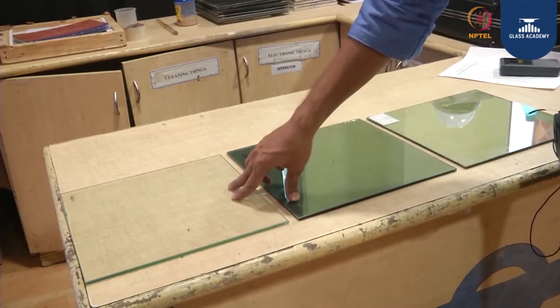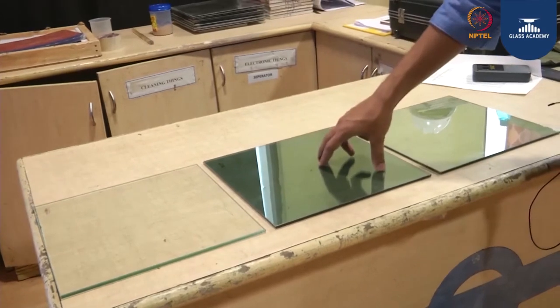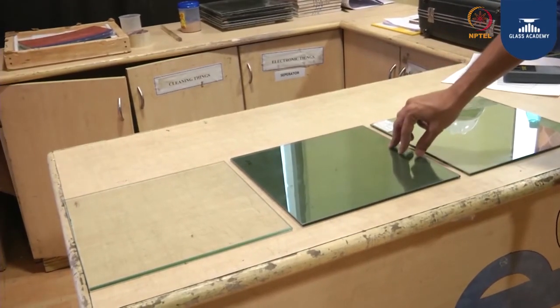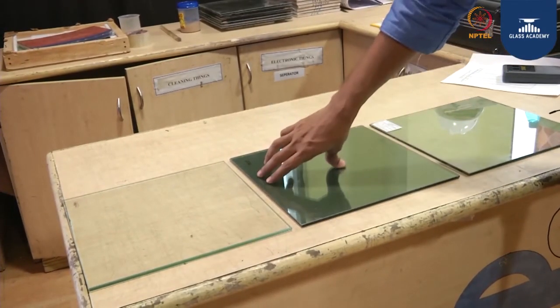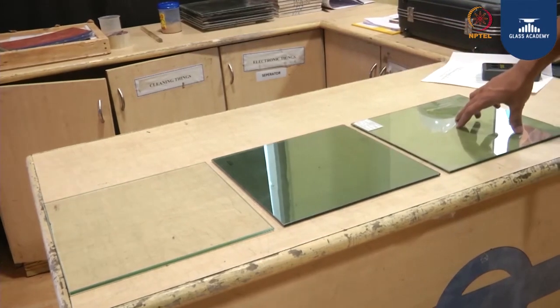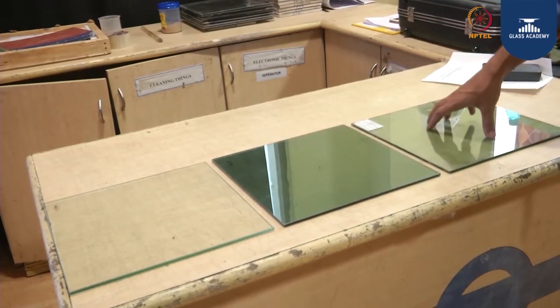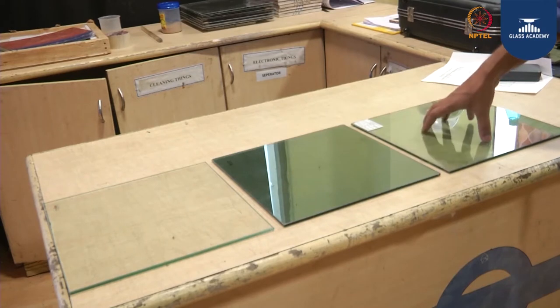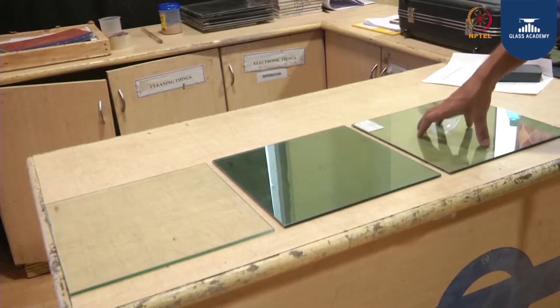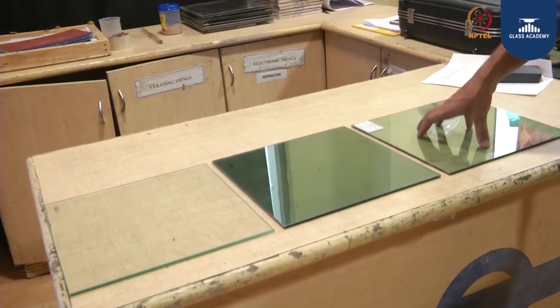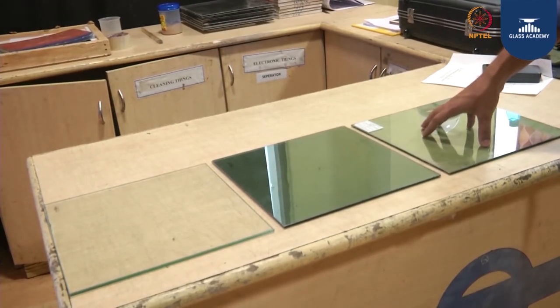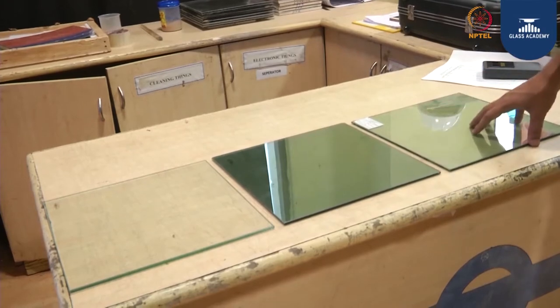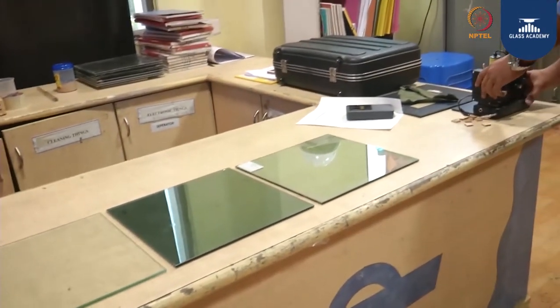When I break a toughened glass, it will break into small fragments. When I break a HS glass, from the impact point, the crack will end at the opposite edge. When I break an annealed glass, it has an irregular shape and the pattern can be anywhere. That is a destructive method of testing. If a glass breaks at the site level, we cannot go on breaking all the glasses. So in order to avoid breakage, we have one more test known as GASP.